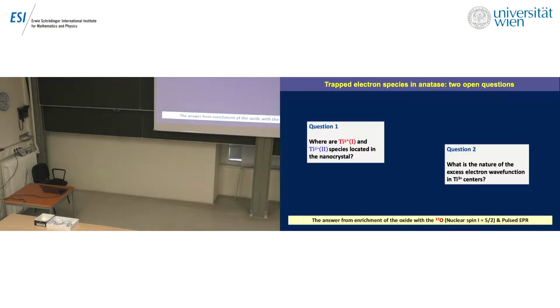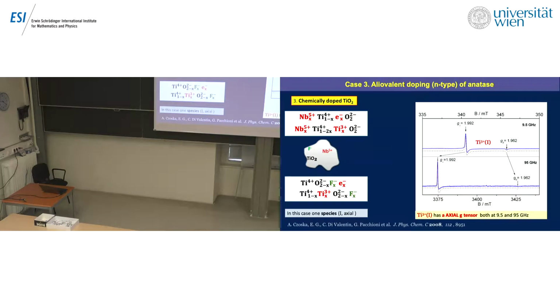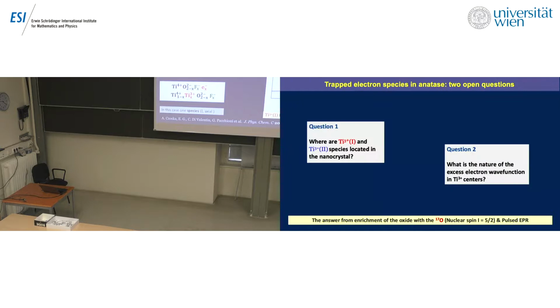So I will focus later on this kind of signal, Ti3+(I) and Ti3+(II). There are two questions now. So where are these two kinds of species located in the nanocrystal? Because you know that there is one crystallographic position in a perfect crystal of titanium dioxide. And what is the nature of the excess electron wave function in this titanium 3+ center? And once again, the answer arrived using oxygen 17. Otherwise, you cannot say anything more.